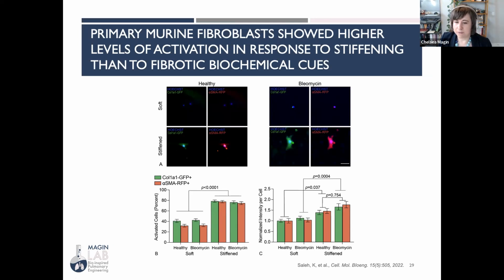If we normalize the fluorescence intensity per cell, so if we say, okay, we're not just looking at whether the cell is making this or not, we're actually looking at how much of the protein the cell is making, we see a very similar difference, but we start to see a trend toward increasing activation in response to the biochemical cues. Overall, we believe that in this model, these results are showing us that the mechanical cues are having a bigger influence on cellular activation than the biochemical cues.